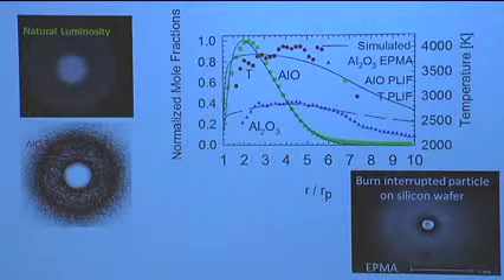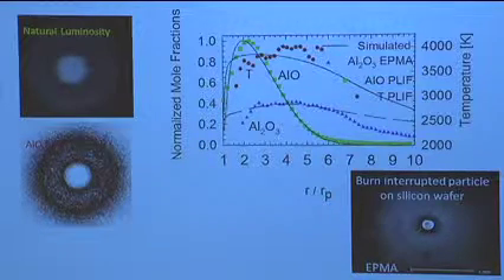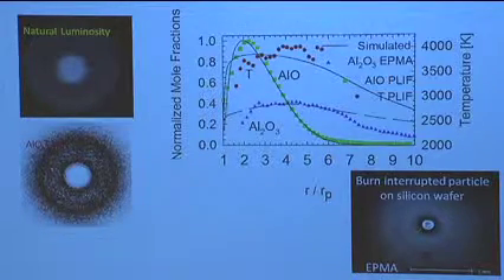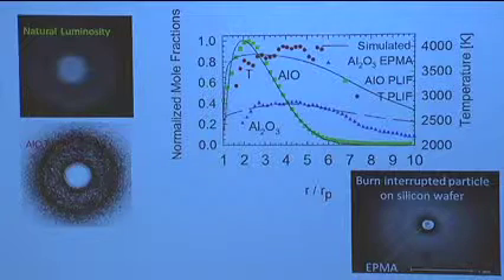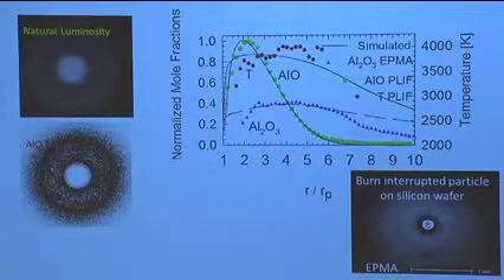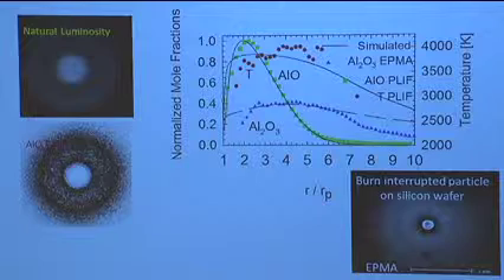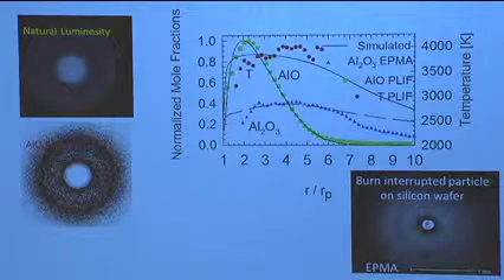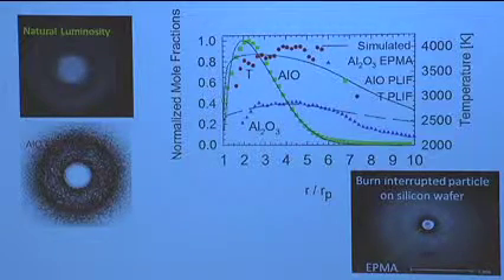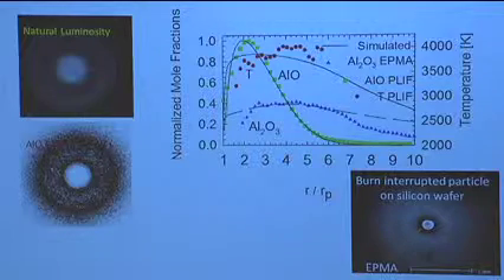And the point I want to show here, unlike a hydrocarbon droplet where I have a relatively narrow peak in the flame temperature, the flame temperature here is very, very broad. It's not a complete plateau because I'm changing sort of the stoichiometry as I move across this, but you can see the plateau is very broad and near the flame temperatures that I showed you on the previous view graphs.